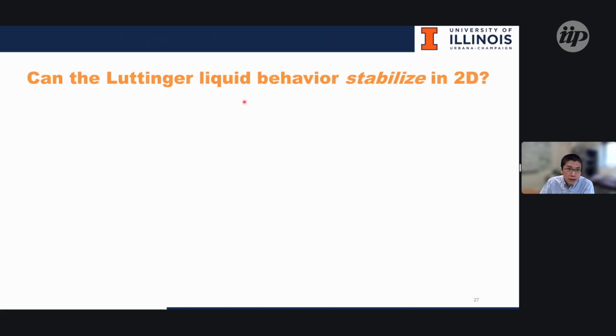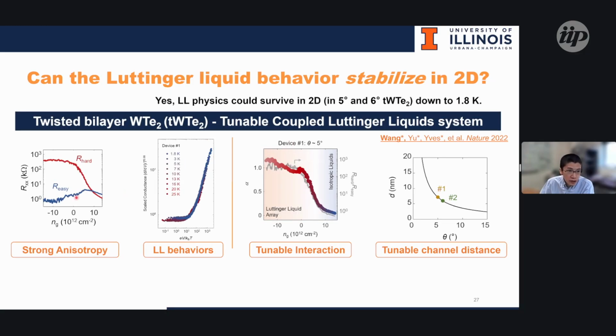So to answer the question I posed earlier: can Luttinger liquid behavior be stabilized in 2 dimensions? The answer is yes. The Luttinger liquid can survive in such a system down to 1.8 Kelvin, captured by the strong anisotropy of the Luttinger liquid behavior, the power law, as well as the tunable interaction and tunable channel distance.